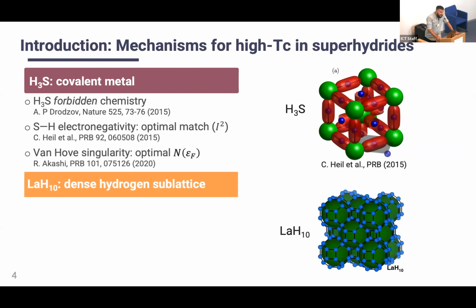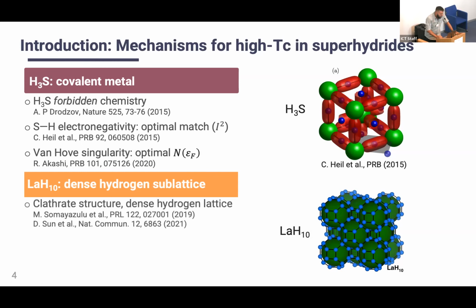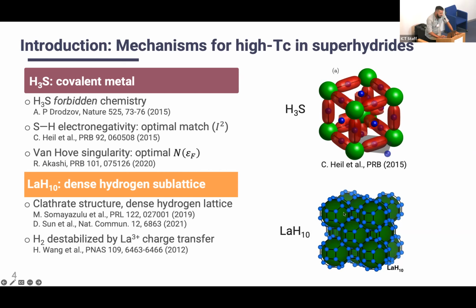The other class of hydrides all belong to these sodalite-like clathrate hydrides that were discussed also this morning. Now, these are characterized by this very dense hydrogen sublattice that is wrapped around a central big metal atom. So in this case, what we see is essentially that this hydrogen sublattice is obtained as a result of a destabilization of the H2 molecule, thanks to the charge transfer from the central metal atom.